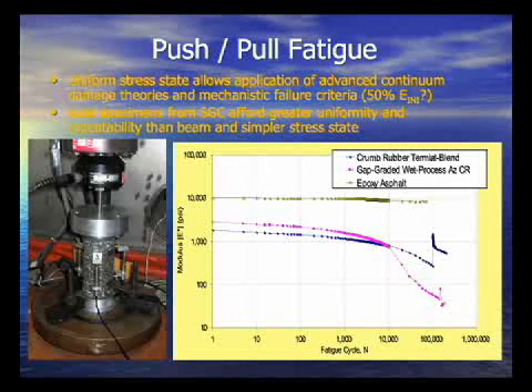I'll also mention that we're able to look at healing in these tests. And I think that healing is really important when we start looking at modified binders, but especially Arizona wet process, because the binder contents are much larger in these mixes. So when you have much more binder, you have much more opportunity for healing. And we can really start to look at how these materials behave.